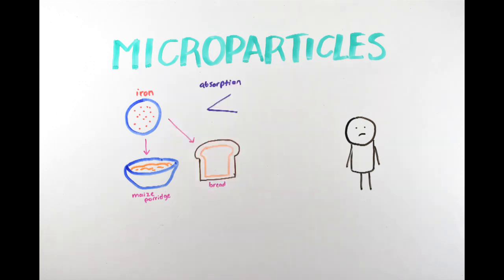Initial results showed decreased absorption of iron using the microparticles compared to unencapsulated iron and indicated the microparticles released their contents too slowly. The polymer coating was reformulated, and a subsequent study found no significant difference in iron absorption between the people who consumed the microparticle-encapsulated iron versus free iron.